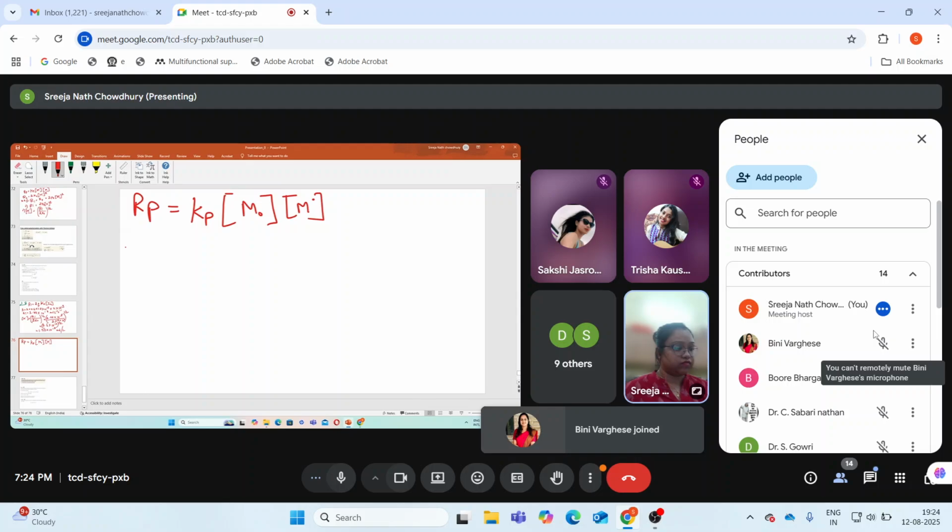This problem is: the benzoyl peroxide initiated polymerization of a monomer follows a simple kinetic scheme with all rate constants and f being independent of conversion. For a polymerization, M0 equals 2 molar and I0 equals 10 to the power minus 2 molar. The limiting conversion p infinity is 10%. To increase the conversion to 20%, would you increase or decrease M0, and by what factor? And would you increase or decrease I0, and by what factor?